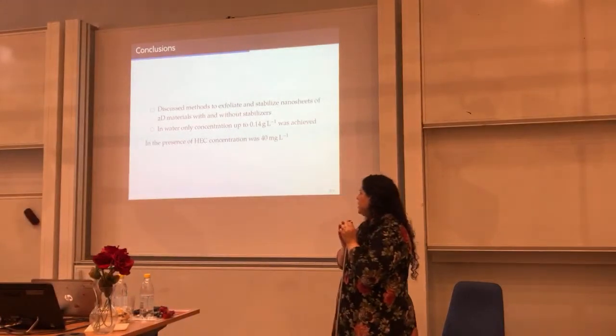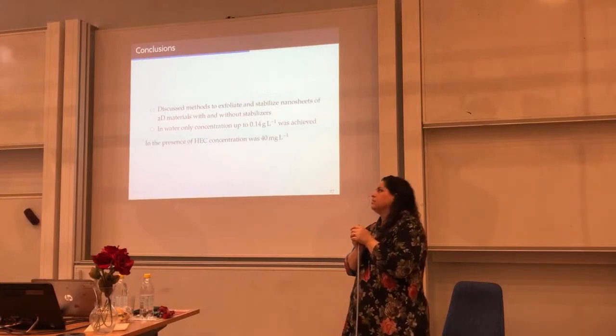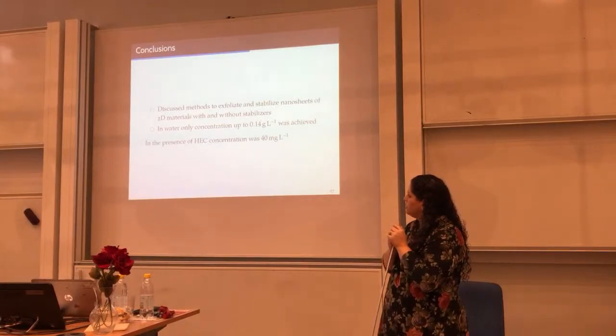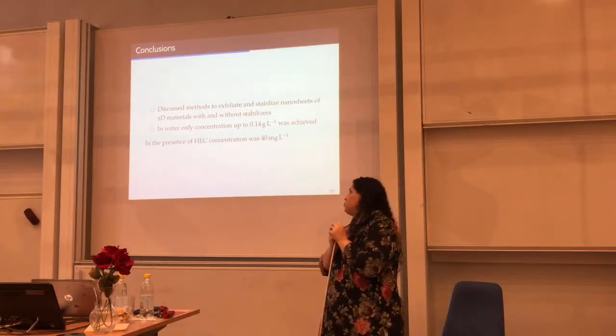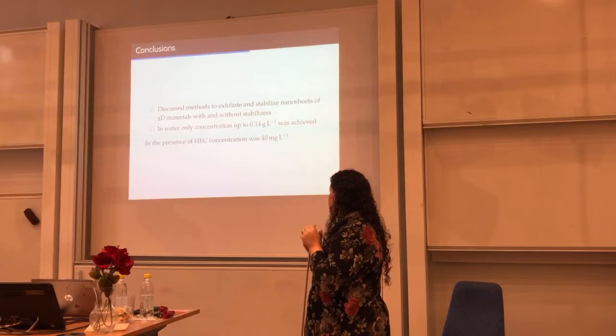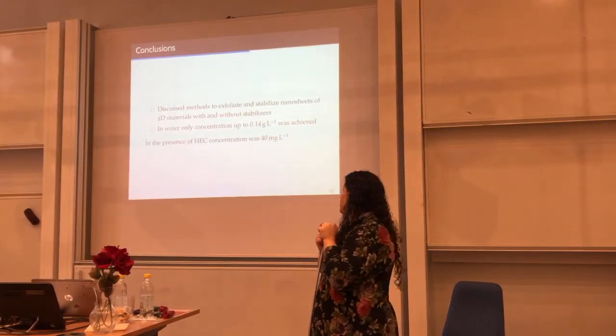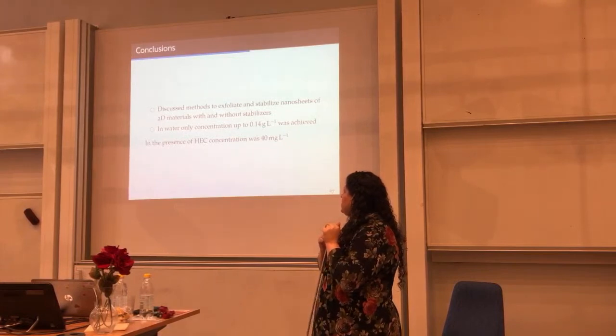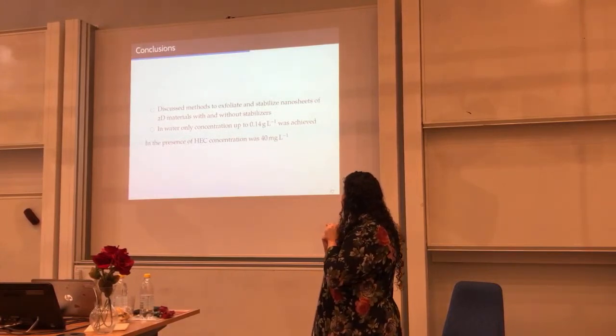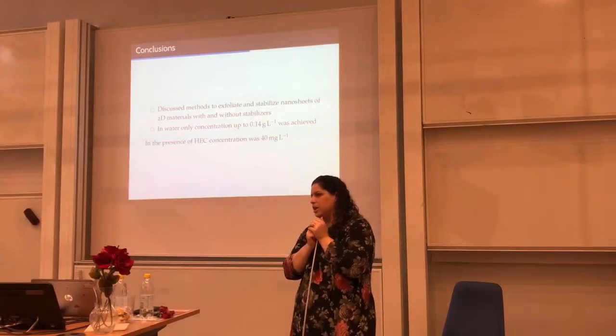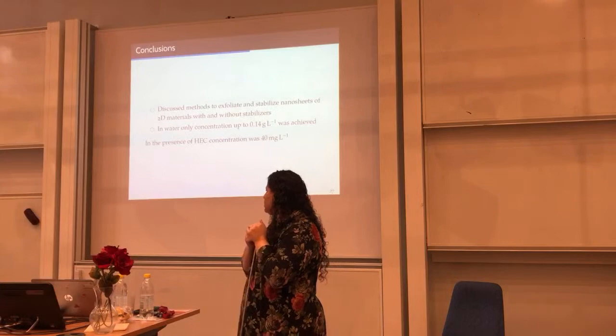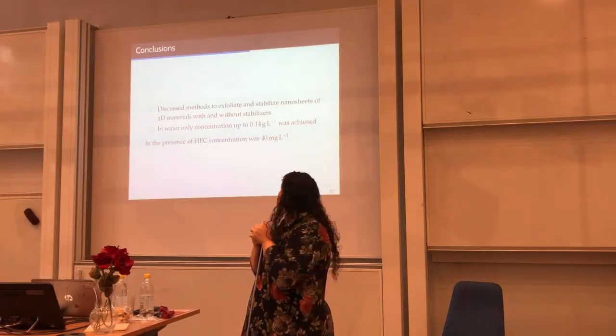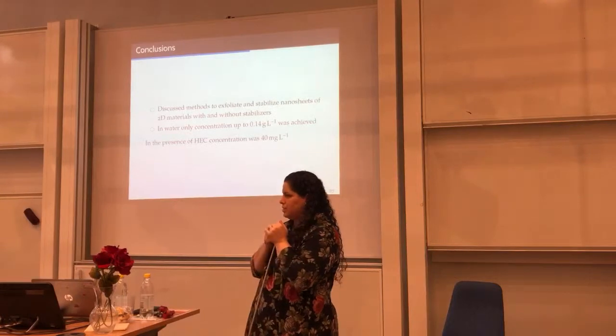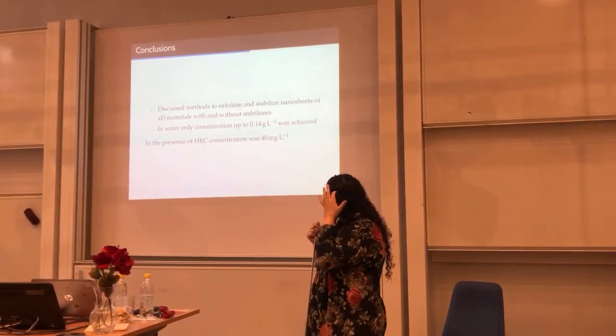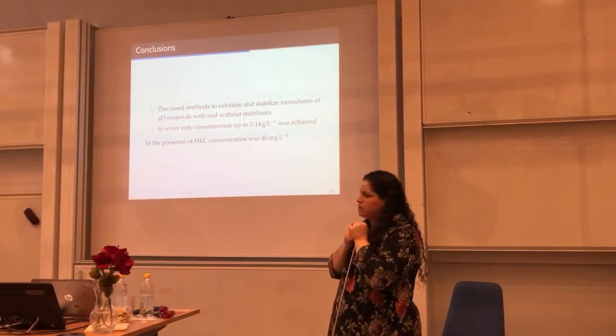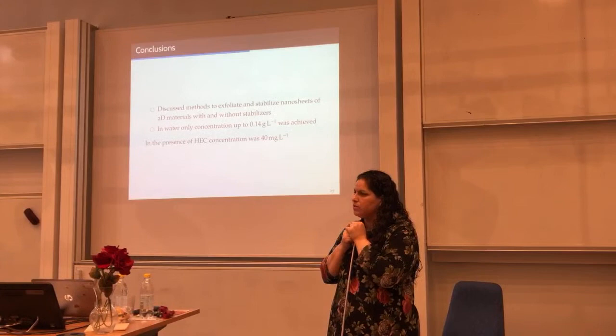So with this, I come to the end of my presentation, and I would like to give some conclusions of what we achieved. We discussed methods to exfoliate and stabilize nanosheets of 2D materials with and without stabilizers. And we achieve a concentration in water of 0.14 grams per liter, which is half of the concentration in organic solvents. So it was a quite good result. And in the presence of HEC, that was our leading paper, let's say this way, this concentration was around 40 milligrams per liter. So it was quite good.